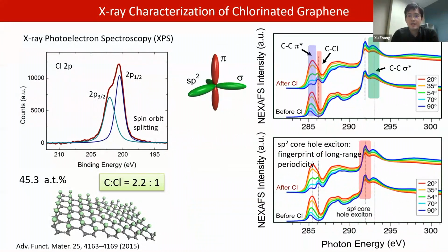We identified a very strong polarization dependence in the carbon pi bond and carbon sigma bond. And next to the carbon-carbon pi bond, we see a clear peak corresponding to the carbon-chlorine bonds. It shows a positive shift in resonance peak of 0.8 eV, which is significant. It explains the strong hole doping effect.